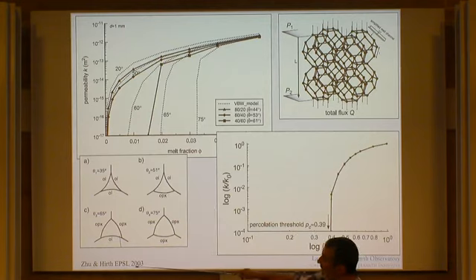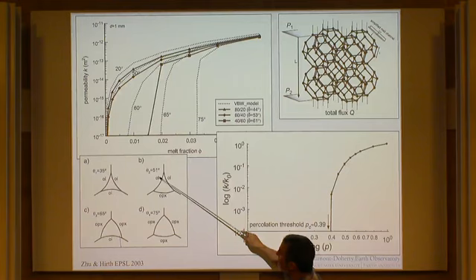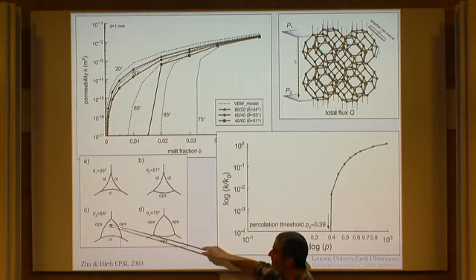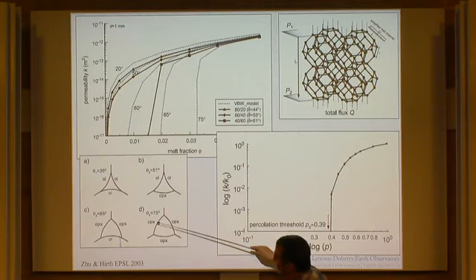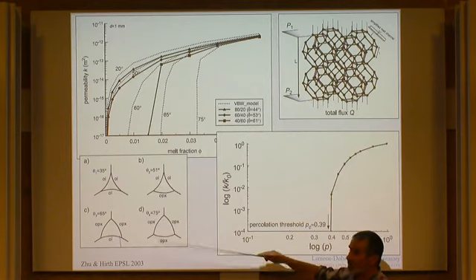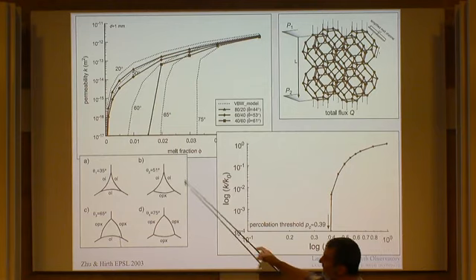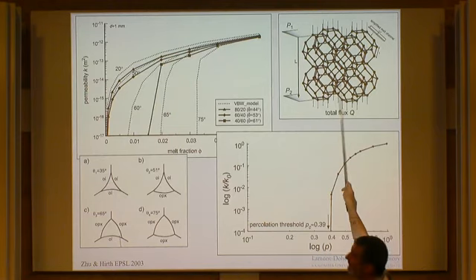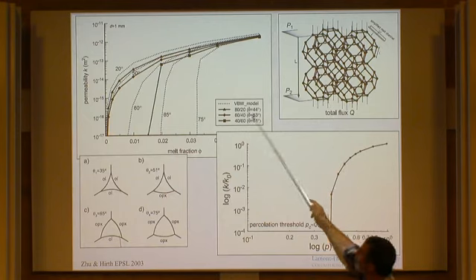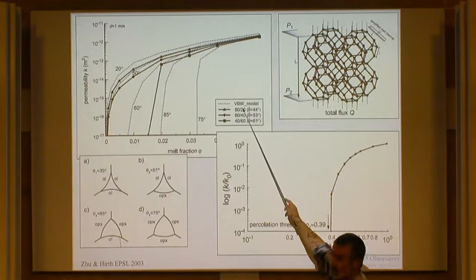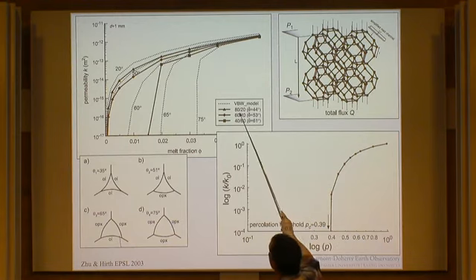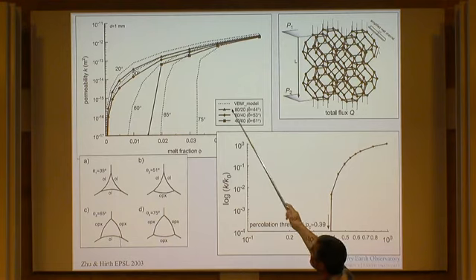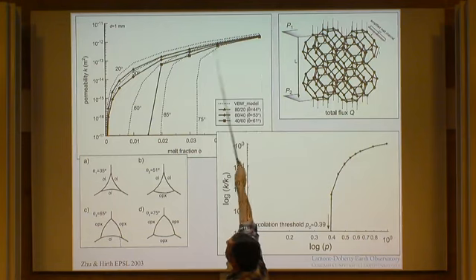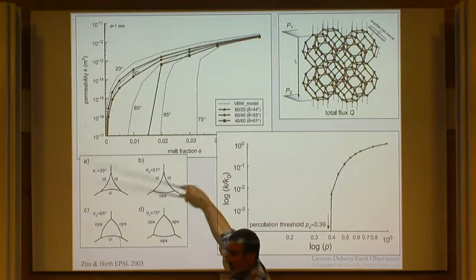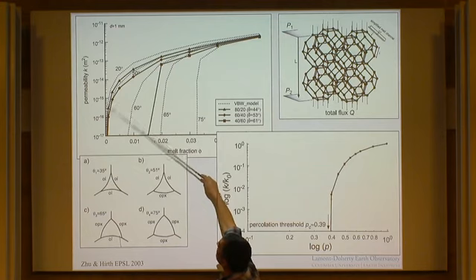So when Zhu and Hirth looked at what happens if you have olivine-olivine boundaries, olivine-pyroxene boundaries, and unwetted pyroxene-pyroxene boundaries, they distributed these combinations stochastically on a grid as a function of the olivine to pyroxene ratio. For olivine-rich rocks, 80% olivine and 20% pyroxene compares very favorably to the von Bargen and Waff model, the numerical model that I showed you and that we tested empirically.